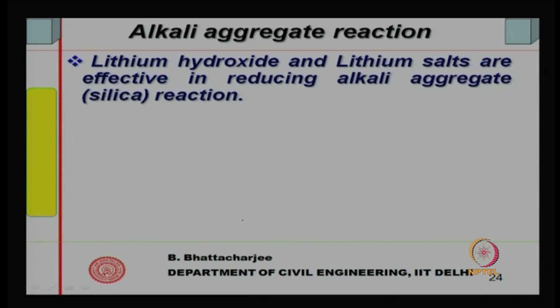sodium and potassium hydroxides that would be present in cement water system, because sodium oxide and potassium oxides are present in cement, right. They are there in the cement usually in small quantity, and this might form sodium hydroxide and potassium hydroxide. Now, these ones will react with some silica minerals, forming alkali silica gel, and this gel can absorb water and expand in volume, resulting in cracking of concrete.